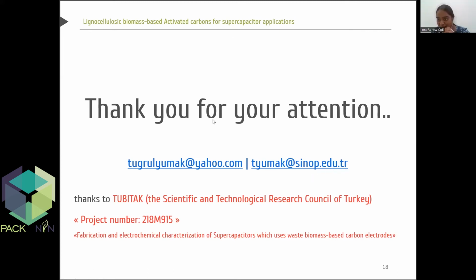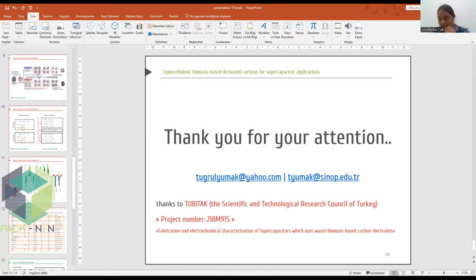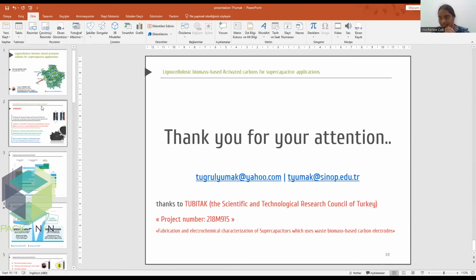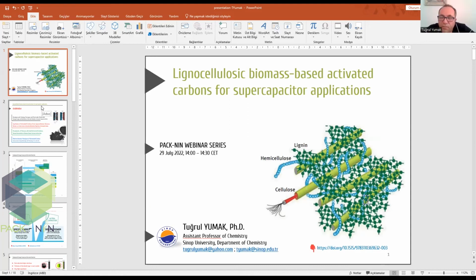Again, I repeat: whether meso or micro porosity should be maximum for maximum capacitance. We need more micropores and mesopores. The micropores are responsible for the charge storage, and the mesopores are responsible for ion transport from electrolyte to micropores. So we need a proper distribution of mesopores and micropores, we need both of them.